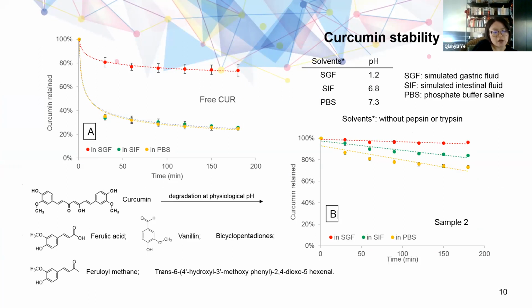As I mentioned before, curcumin is unstable at neutral and physiological pH. Its degradation products include ferulic acid, vanillin, etc. This stability test shows that free curcumin was degraded by over 60% within 30 minutes at neutral and alkaline pH. By comparison, more than 70% of the curcumin was stable in the curcumin-WPI complex in the PBS buffer, SGF, and SIF after 3 hours. This reveals that the generation of curcumin-WPI complexes effectively enhanced the stability of curcumin.